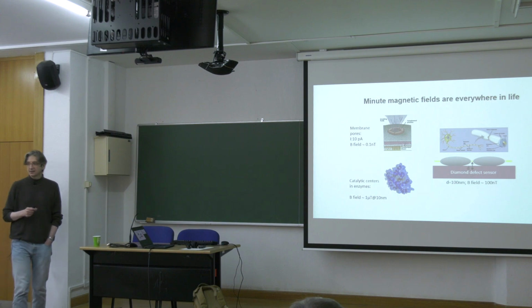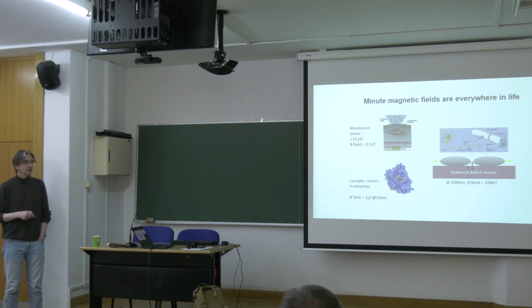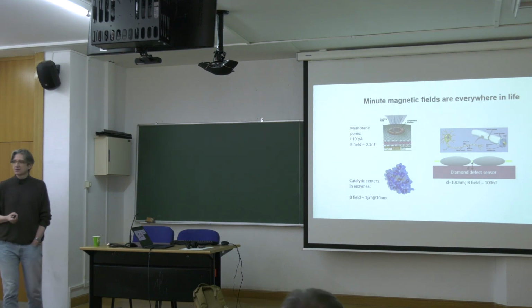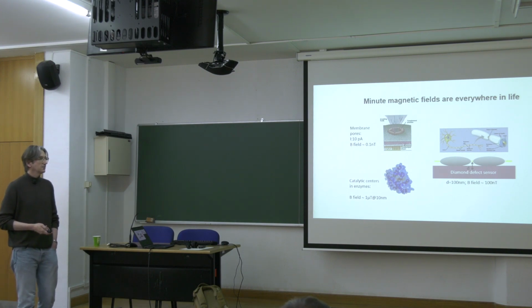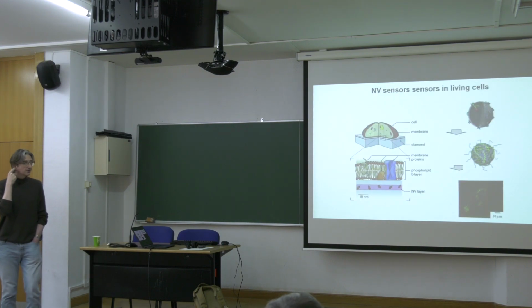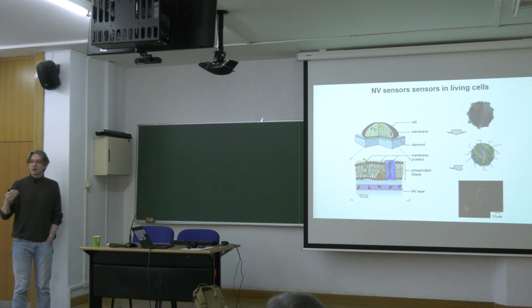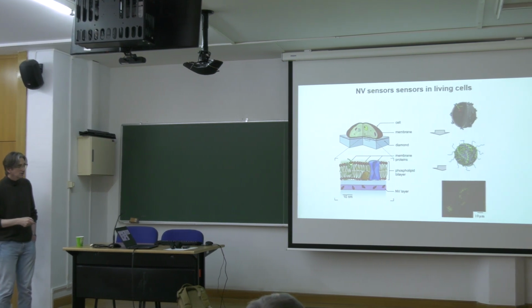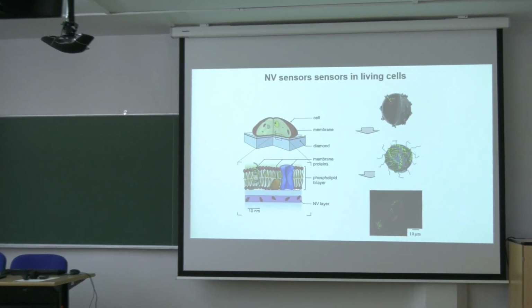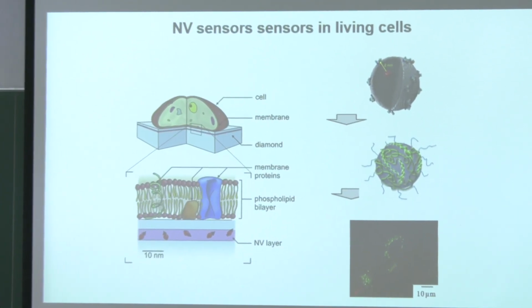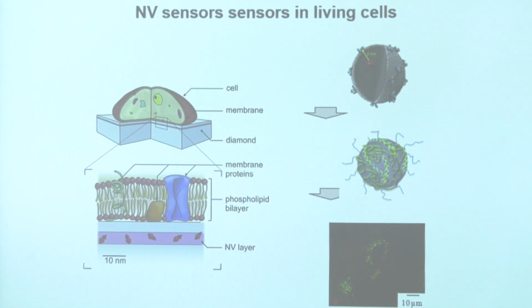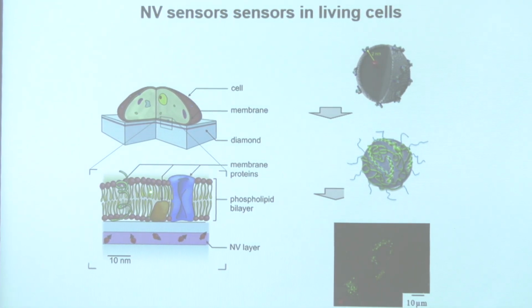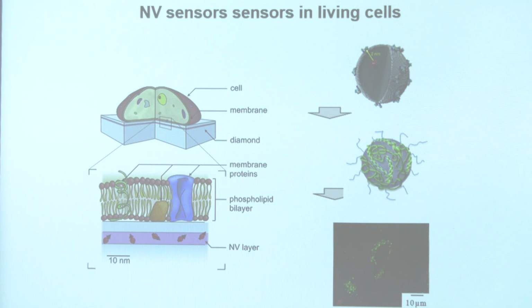And those are very exciting events, because they are very hard to measure or access with other techniques, except if you have magnetometers that you can approach to molecules at very, very small distance. And if you think about the measurements themselves, of course you need to get close, and there can be different modalities. Either you take a diamond with NV centers created very close to the surface and you put a cell on it, and in this case you can sense something very close to the layer of NV centers, so perhaps membrane proteins or some events that are happening very close to a biological membrane.